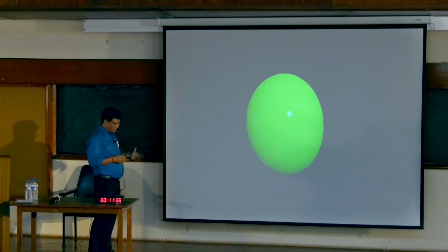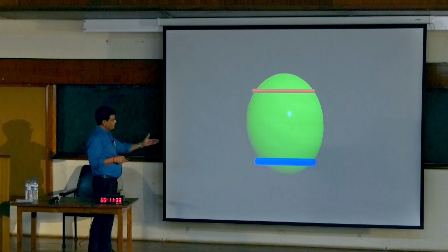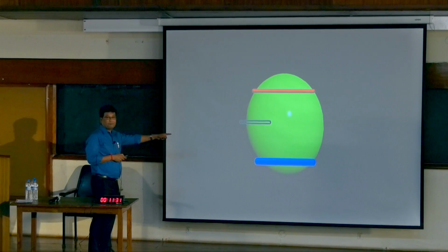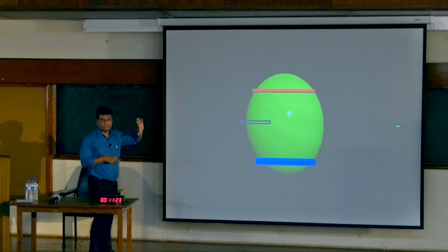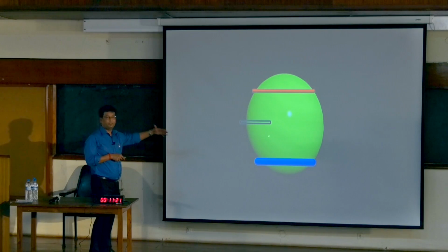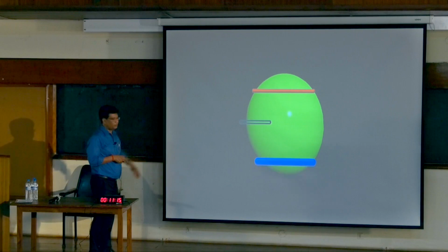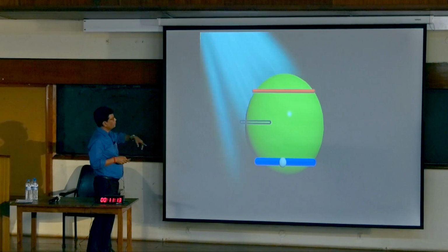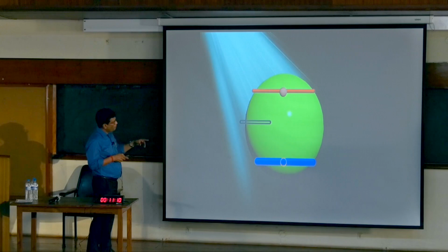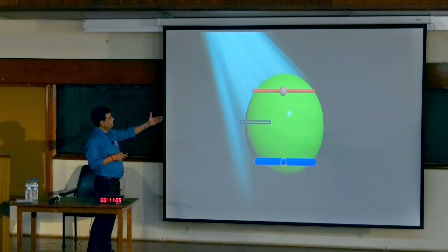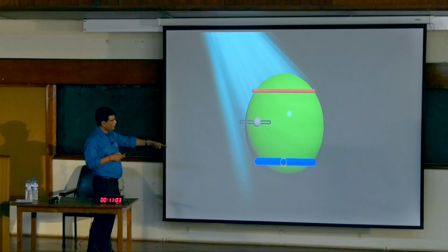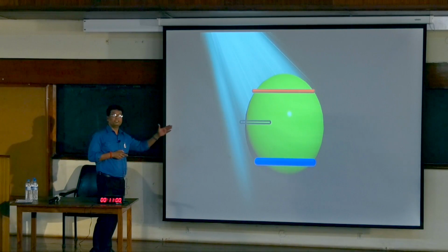This is the quantum dot again; I want to explain again. This is the valence and conduction band, and this is the trap state. If your quantum dot is very good, then you can consider only the trap state, not the surface defect state. I am considering only the trap state because our quantum yield is very good, and the full width at half maximum is 25, which means a very good quantum dot. When the electron goes from the valence to the conduction band and recombines, it generates light. This is a radiative process. Now, if that electron goes to the trap state and recombines, it will not generate light. This is a non-radiative process.